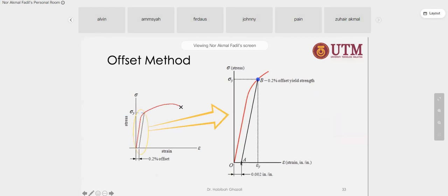So 0.002, let's say, and then from this point, the strain value at 0.002, you construct a line parallel to the elastic line, and the stress at this intercept is the yielding where the yielding will occur. First you define a point at 0.2% of the original gauge length. Original gauge length is a constant value